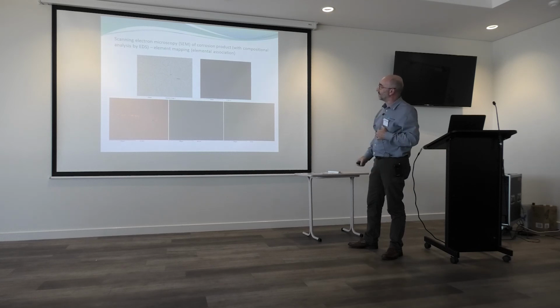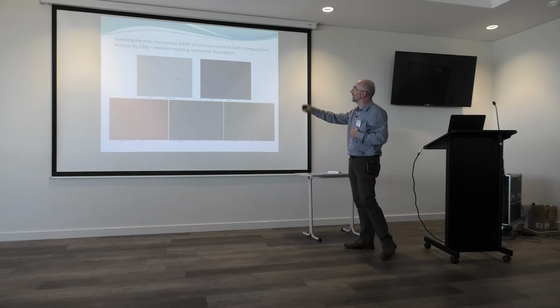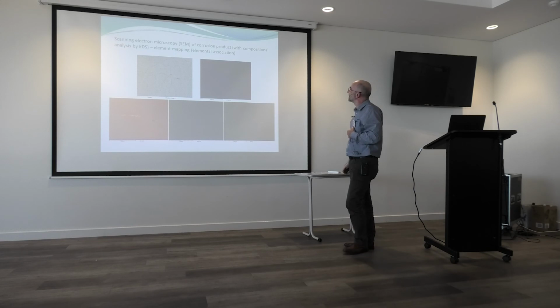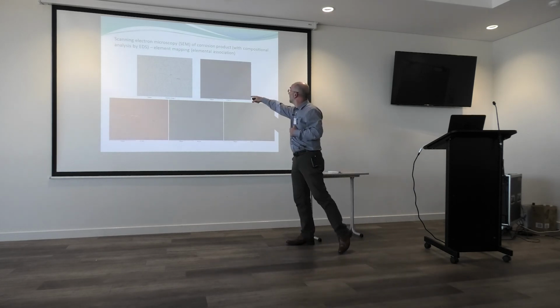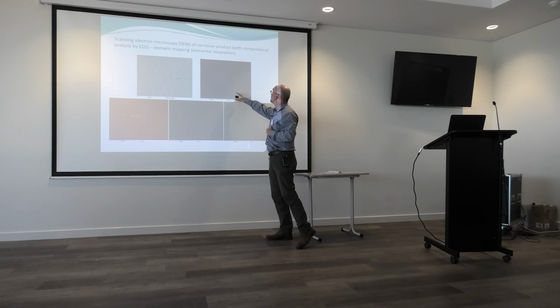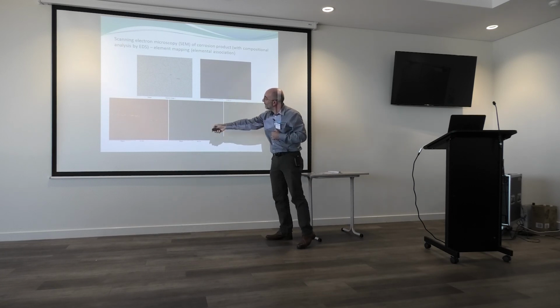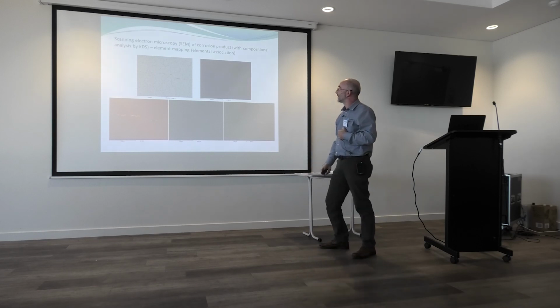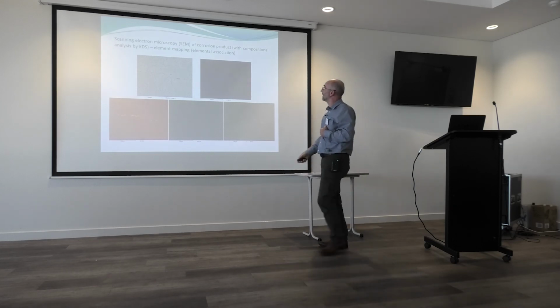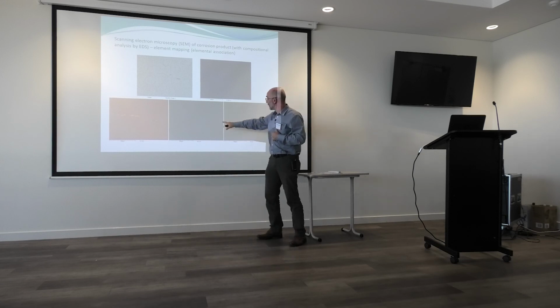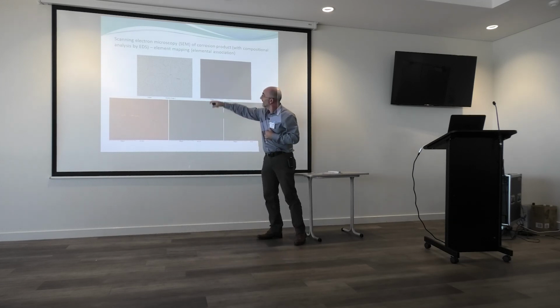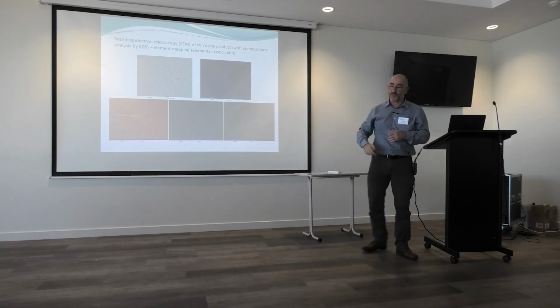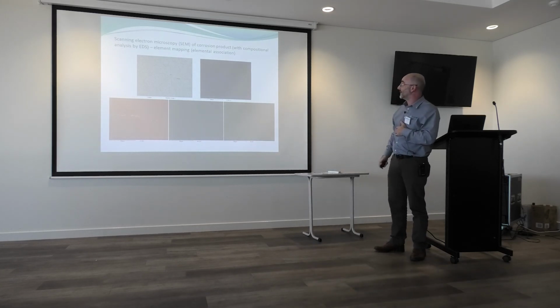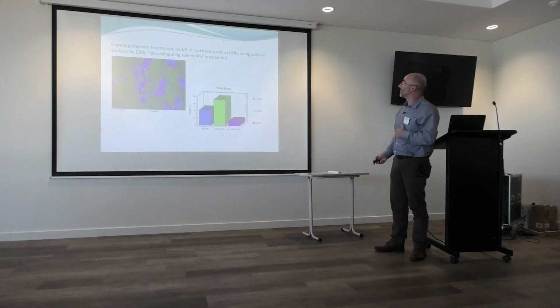Some of the other stuff we're doing is elemental mapping, as Paul was mentioning earlier on. There's an etched microstructure there and an electron image on the top left, and it's a little bit hard to see, but you can see the carbon map showing the carbide precipitates on the grain boundaries, and then the chromium map showing the chromium carbides at the grain boundary, and then there's a big inclusion of niobium sulfide related to that. So some of the work that we do is varied. I don't claim to be a metallurgist, but it's always interesting when the guys come in and show these unusual samples, and we get to work with them.